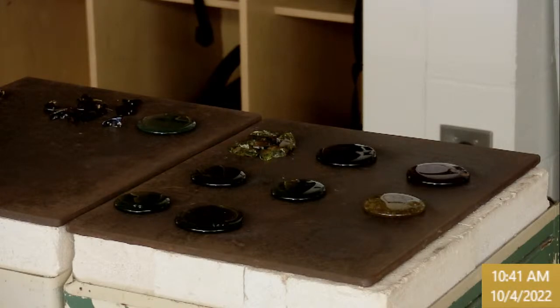Now, he also mentioned the box. We're gonna get it in the box. What's that mean? Well, this is hot glass that still has lots of tension inside, and to make it stable, unlike what we're doing, we're cold quenching this glass on a piece of metal. We're just letting it chill to room temperature quickly. If you were to pour it and then immediately place it into another furnace that's at an annealing temperature, so if it melts at 1200, let's say we set another furnace to 800, maybe 700 Celsius, away from that melt temperature, but still hot enough that the silicon-oxygen-silicon bonds that are stretched can then break and join with something that's closer to it. It relieves that internal stress before it gets locked into this extended posture.